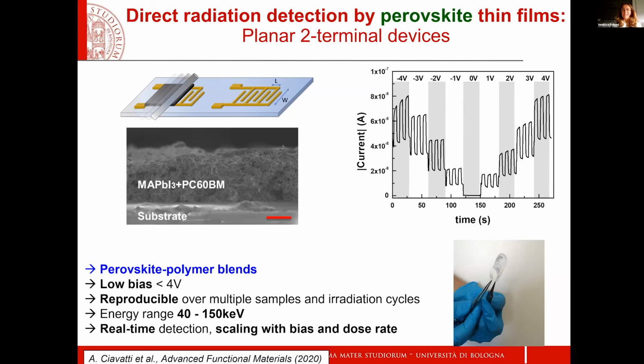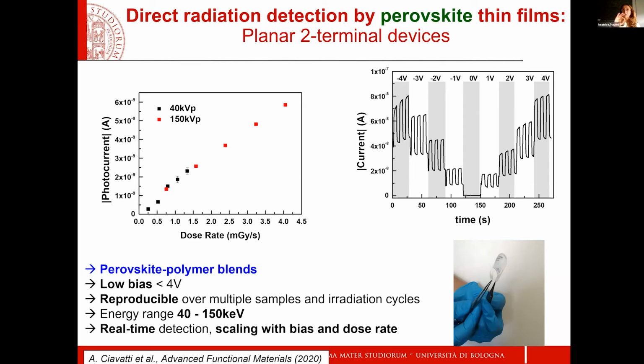Last information I'm giving you today is that you don't need such a complex solar cell heterostructure to have a good thin film perovskite detector work. Here I'm just showing you a 2-terminal device where the active layer is a thin film, in this case of a blend of perovskite and polymer. And you see that the response under on-off X-ray beams, in the range here, I'm just reporting the 150 kilovolts, but it goes all the way down, is really reproducible, operating at low bias and very reliable. So again, the focus here is on the material. And I think there's a lot that we can do on playing with this material that allows us to obtain, as you can see, very nice linear response for dosimetry.